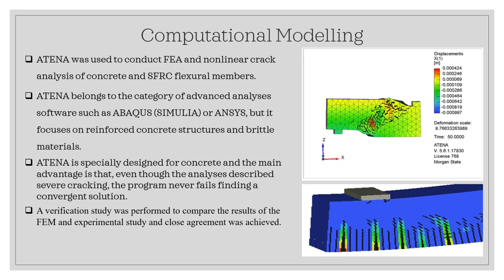And the other factor that we consider, as I said, is volume fraction or fiber content. Based on the previous studies that recommended between 0.5 to 3%, we also consider that with small intervals to try to define different scenarios, so that we can better evaluate the performance in different situations with different fibers, and combinations of these variables. The other thing was aspect ratio. The aspect ratio that we consider in this parametric study was between 55 to 500, also with small intervals to enhance the accuracy of the result. Regarding the compressive strength of the concrete, just the concrete material, we consider 32 to 56 megapascal compressive strength, of course, at 28 days age.